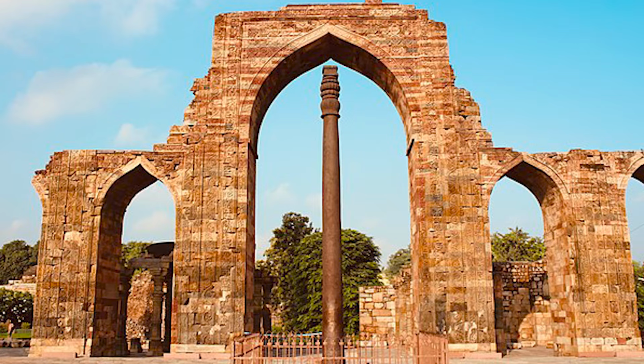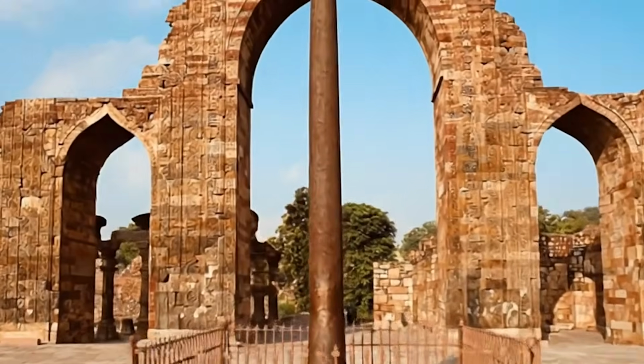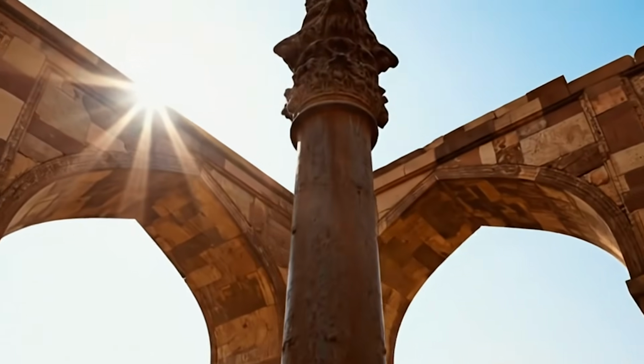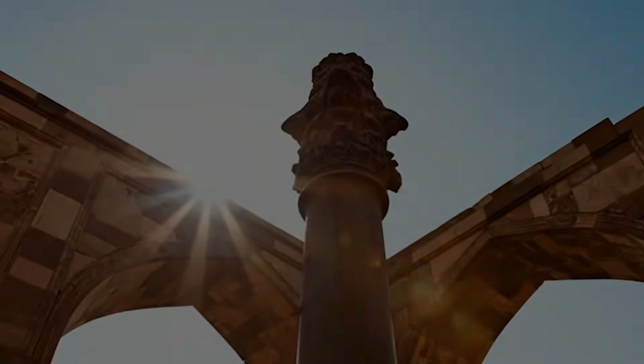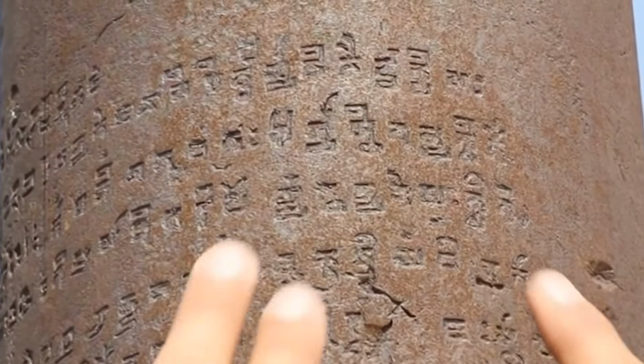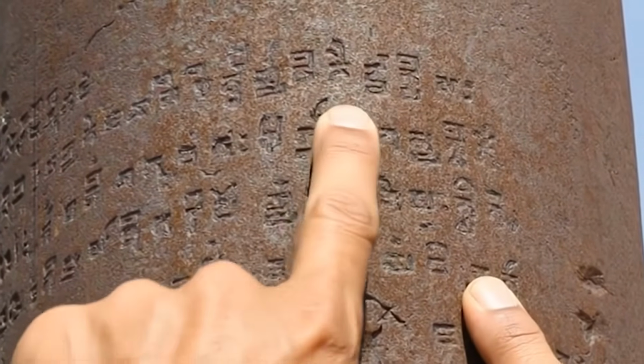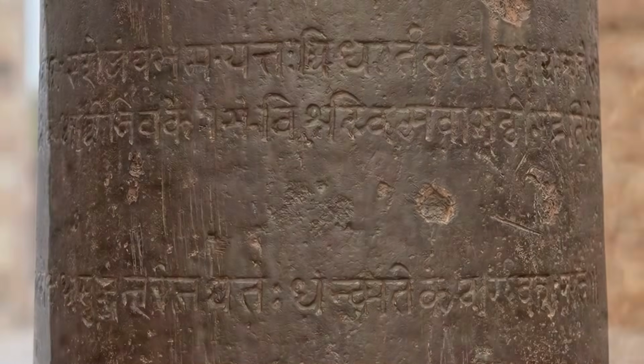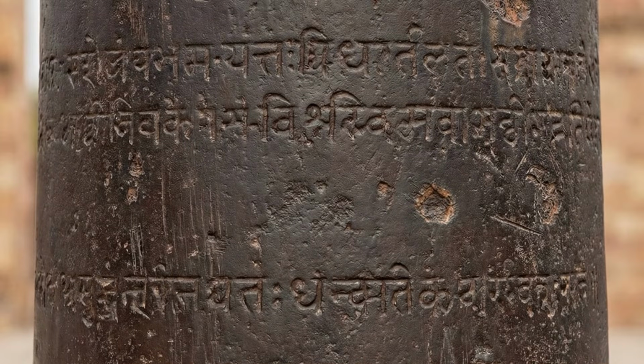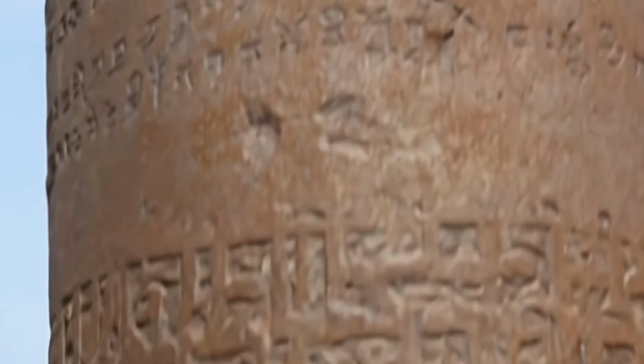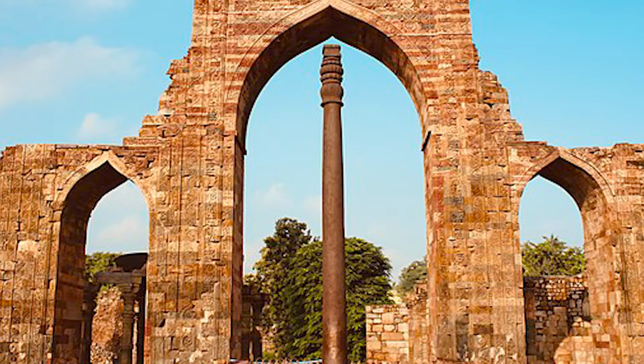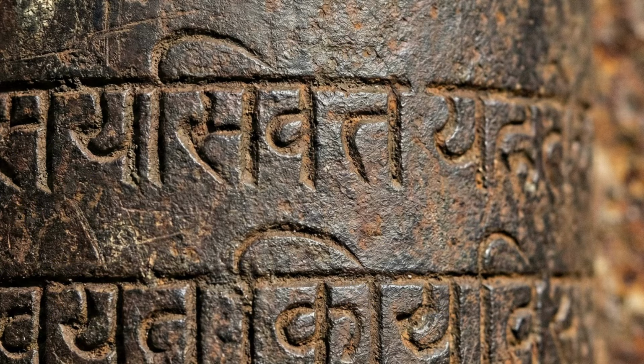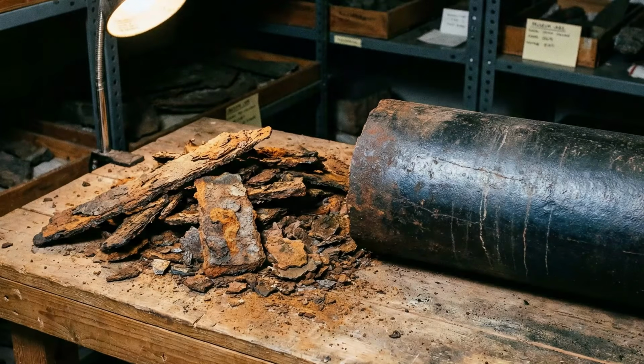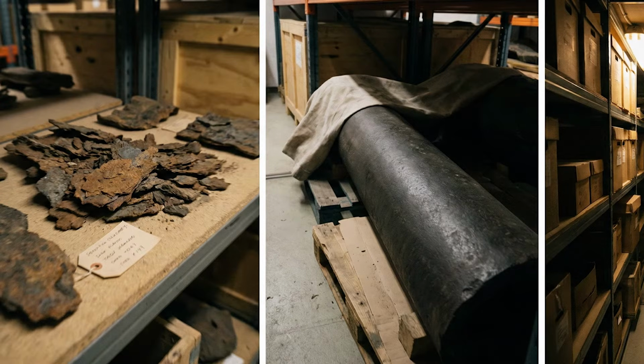In the courtyard of the Quwwat-ul-Islam Mosque in Delhi stands a pillar of iron, roughly 23 feet tall, weighing more than 6 tons. It was forged during the Gupta period, sometime around 400 CE, and despite 16 centuries of exposure to Delhi's monsoons, humidity, and seasonal temperature swings, it shows almost no rust. A thin coating of oxide has formed in some areas, but the pillar remains structurally sound, its Sanskrit inscription still legible, its iron core intact. For a metal that normally corrodes aggressively in humid environments, this is remarkable.